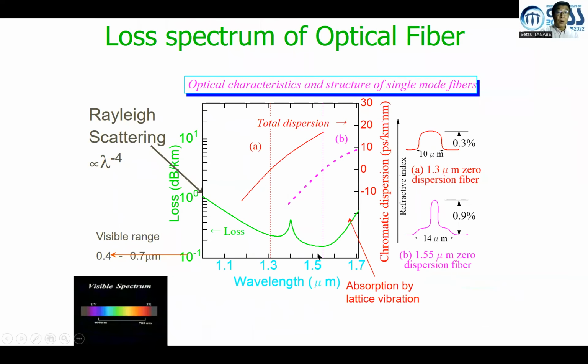So this is an optical loss spectrum of a silica-based optical fiber. In the short wavelength region, Rayleigh scattering, which is proportional to the inverse fourth power of wavelength, is dominant. At longer wavelengths, multi-phonon absorption becomes dominant. Because of that, the 1.55 micron region is the minimum loss wavelength region, which coincidentally overlaps with the emission wavelengths of erbium.